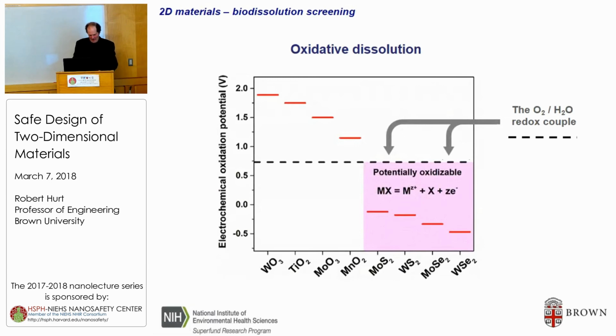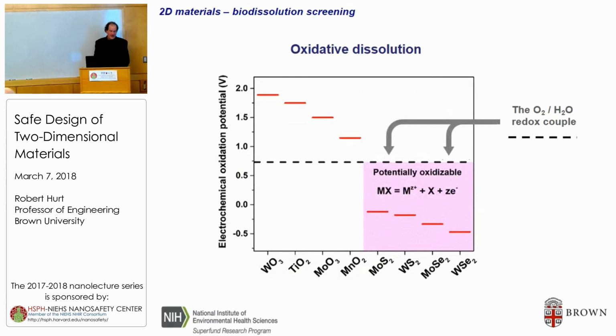And the other question we have from online is, would you have any comments on how the range or size distribution of the layered materials based on different exfoliation methods could impact the colloidal properties and dissolution? Yeah, we haven't studied that either, but dissolution, of course, is surface area dependent as a first-order term. And so there's no doubt that the finer the material is, the faster any dissolution process would be. And like with molybdenum disulfide, since it takes a month or something to dissolve, the size could make a big difference.